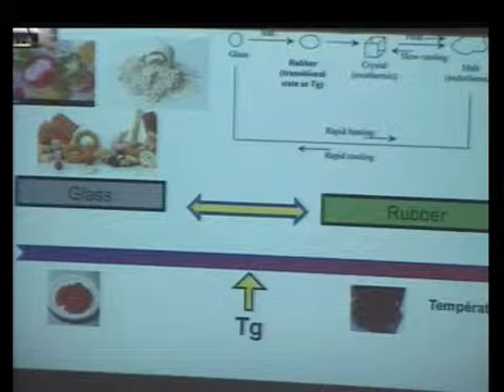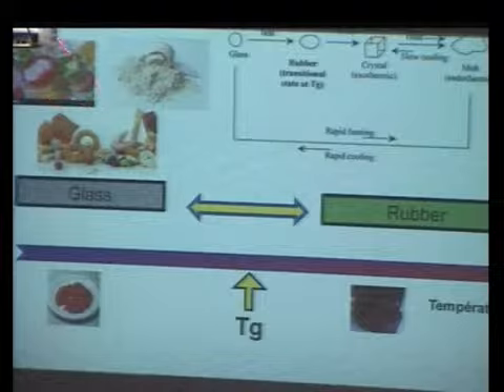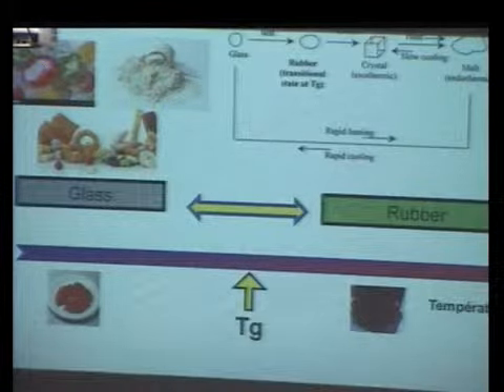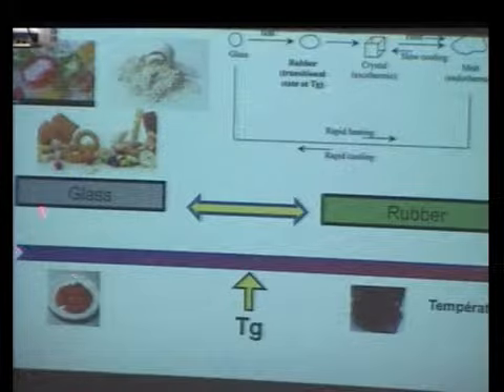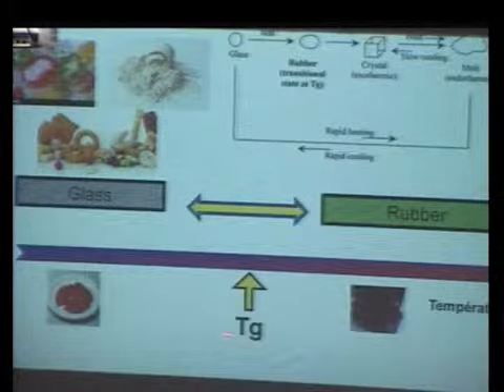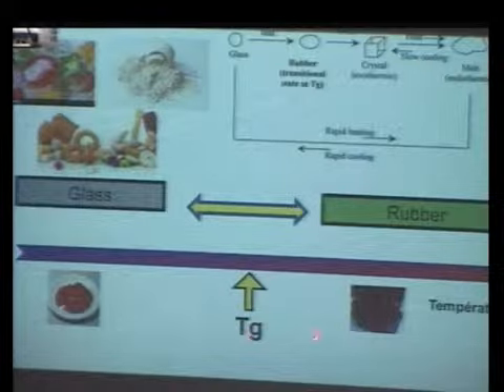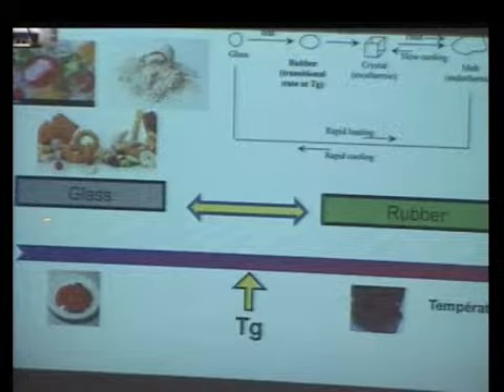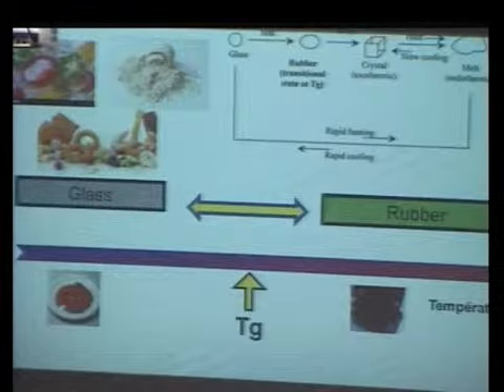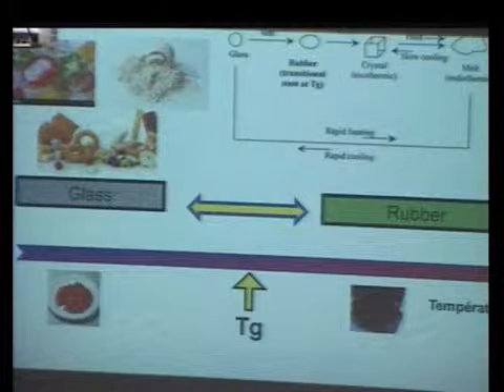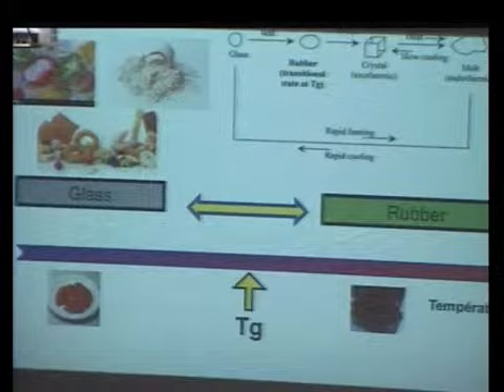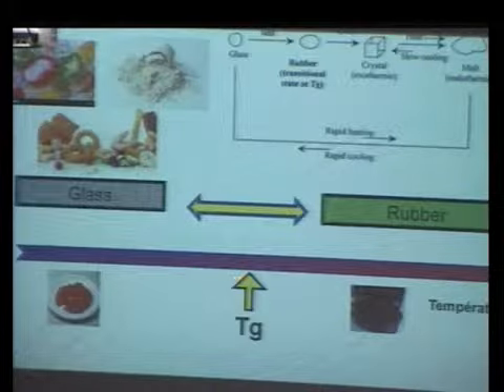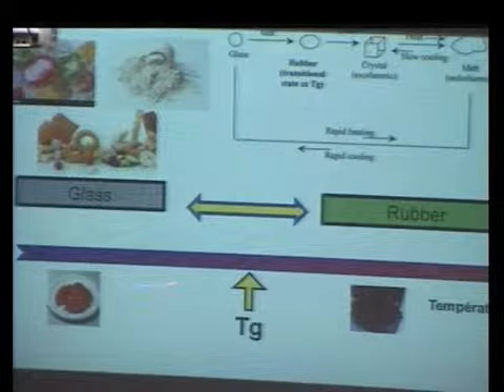It means that at the beginning you have a snack, a powder, a sweet, very nice, like a glass, very crisp and so on. For example, the glass transition temperature is 60 degrees, and the storage temperature is 20 degrees. So you are far from the transition, so it will be okay. But if this product takes up some water, if the water content increases because it's not packed, it's not protected, you have a decrease of the glass transition temperature. And then your product will be in danger.